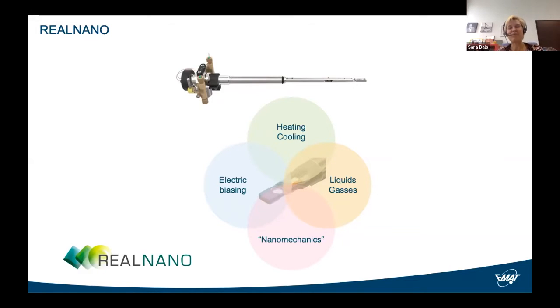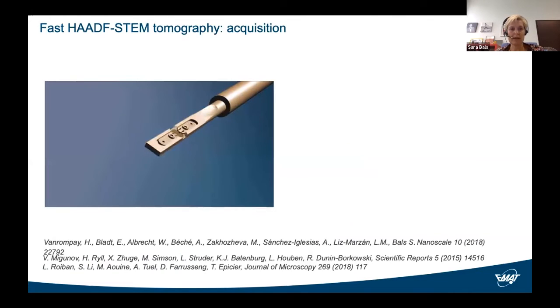Now that's all great, but unfortunately, performing a three-dimensional characterization using these holders is not a simple method of plug and play. And there are several technical but also fundamental aspects that we need to overcome. Now, one of the most important things is illustrated here. And so this is again the movie on how we acquired the tilt series. And what you see is that we tilt a holder and then there's a small pause. And during this pause, we realign the focus or we put our object back in the field of view. And as a result, even for a trained user, it takes at least an hour or so to collect a full tilt series of images.